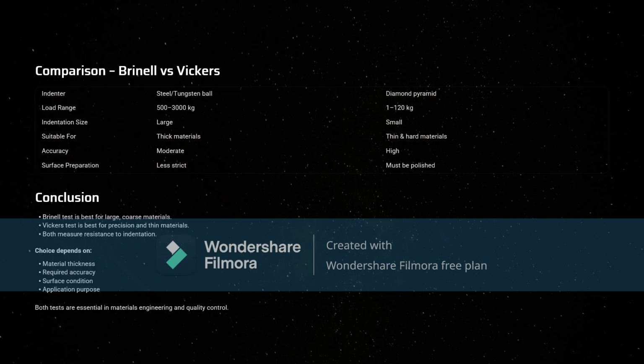The indentation size of the Brinell hardness test are large, and as for the Vickers, it is small. Brinell hardness test is suitable for thick materials, and the Vickers hardness test is suitable for both thin and hard materials. Accuracy of Brinell hardness test is moderate, and as that of Vickers is very high. In Brinell, the surface preparation is seen less strict, as that of Vickers. It is followed very strict, and it must be smooth and polished.